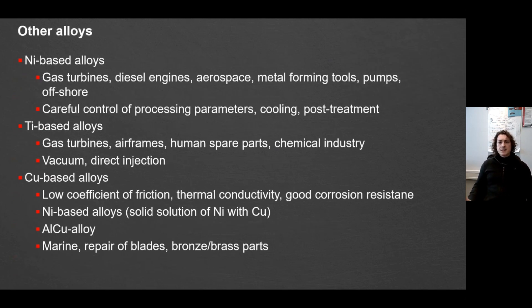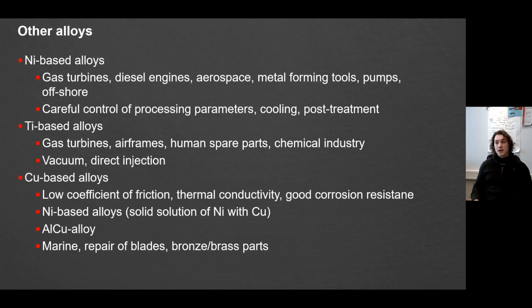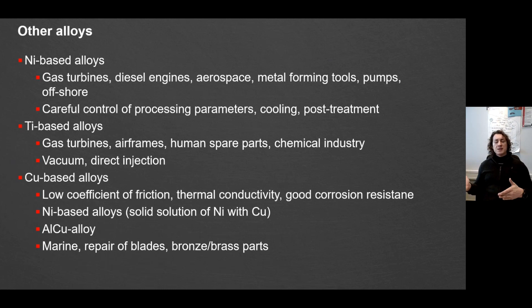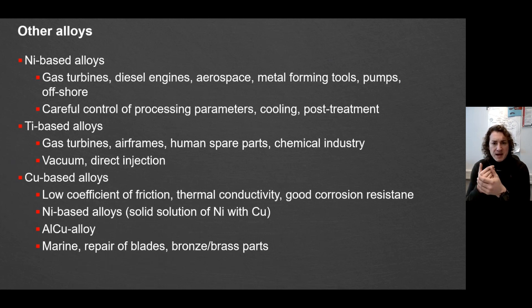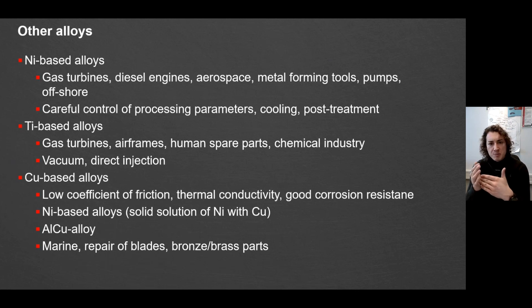Some other alloys, just to give you a brief overview: nickel-based alloys behave in a very similar way to austenitic stainless steels, so the main risk is related to hot cracking, especially if you work with Inconels. In the case of titanium-based alloys, you should primarily avoid interaction with oxygen, so you need a really strong shielding gas atmosphere or vacuum chambers. In some cases you can try to work with wires, which give you much better control of your conditions compared to powder materials, helping you maintain a stable process. The last group is copper-based alloys, which are also very difficult to work with due to back reflection and lower absorption of laser light by copper, leading to a very complicated repair process. There are some companies that can do it, and this is also a niche product.